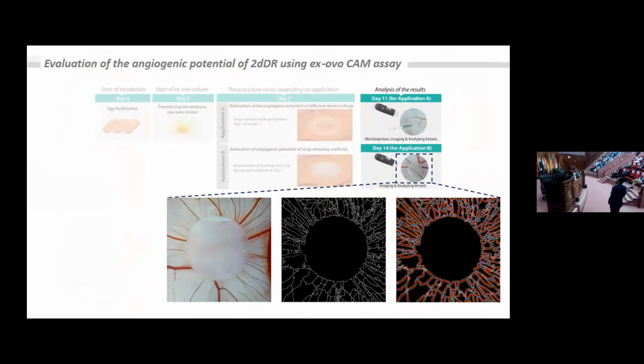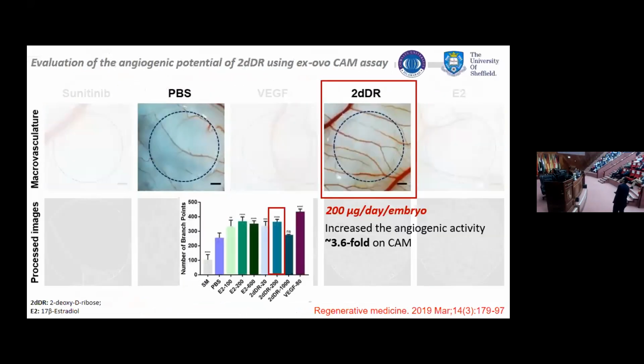And this is how our samples look at day 14, when the experiment is finished. This is a very interesting slide: this egg was treated with PBS control, and this one was treated with 2-deoxy-D-ribose, 200 micrograms per day per embryo. This was the stage where we were trying to understand how much dose of 2-deoxy-D-ribose we would need to load on the dressings. What we saw is that this concentration increased angiogenesis around 3.6-fold compared to the PBS.